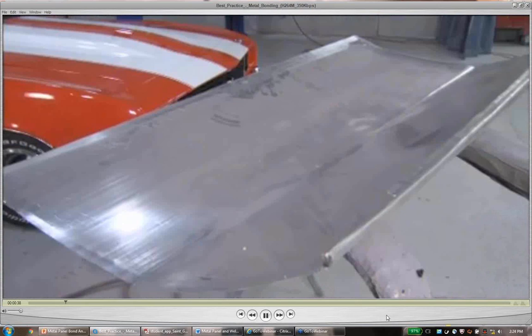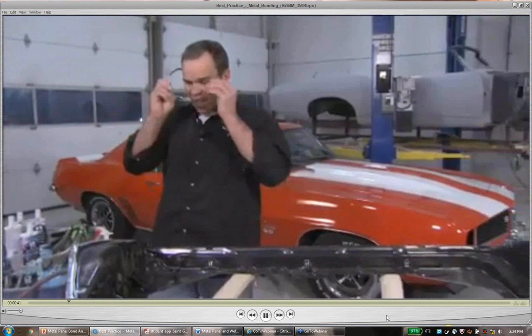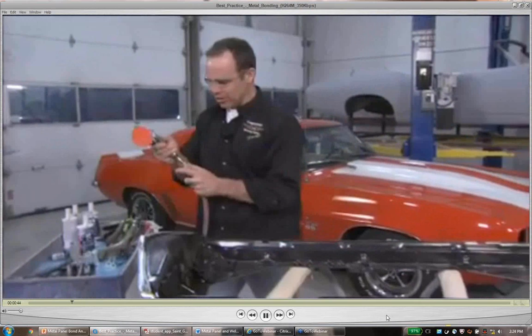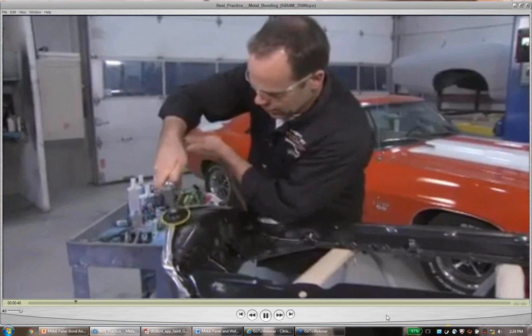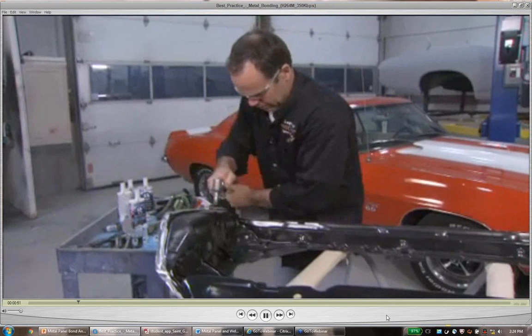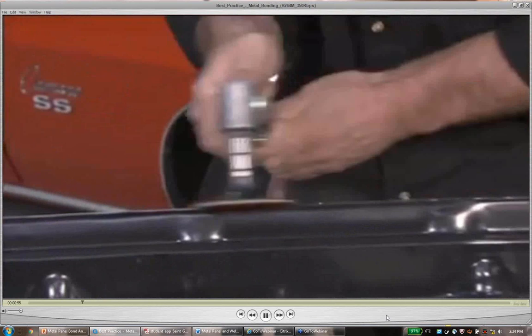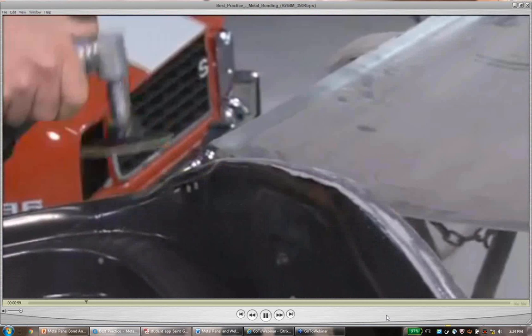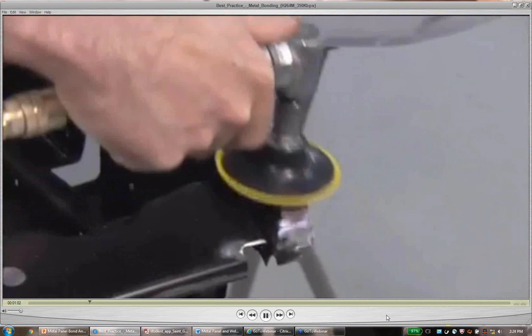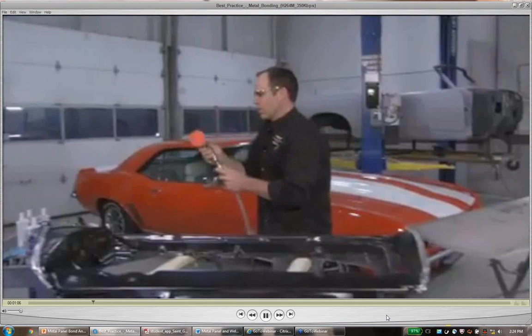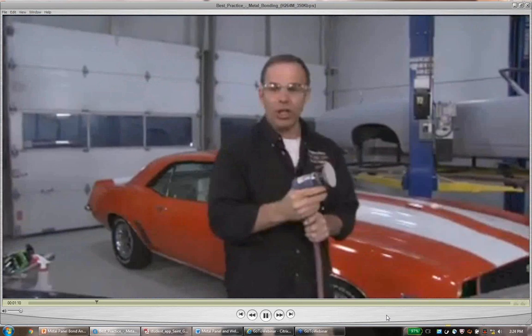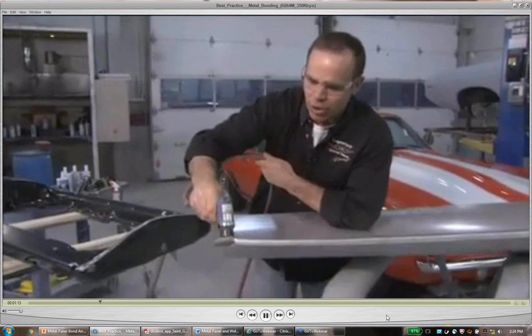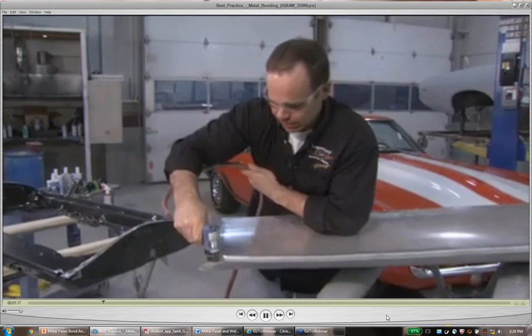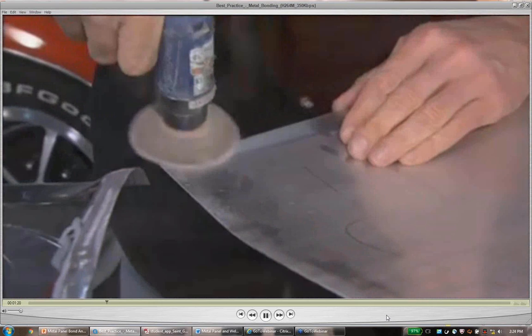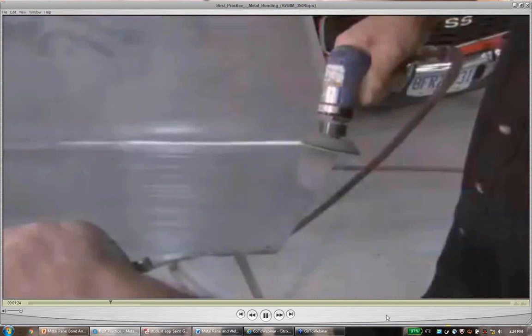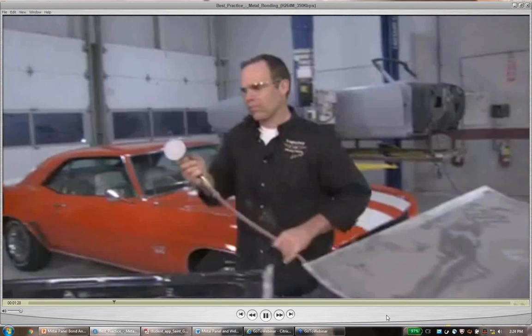Well, the first step is to make sure that both panels are nice and clean, but you don't want to ever mix up the disc. We're going to start with a 50 grit on the steel. Now you want to make sure that you switch out the discs because you're never going to mix an aluminum and a steel grinding disc. This one we're going to go with an 80 grit. Once you're finished that, you're just going to blow off the panels.